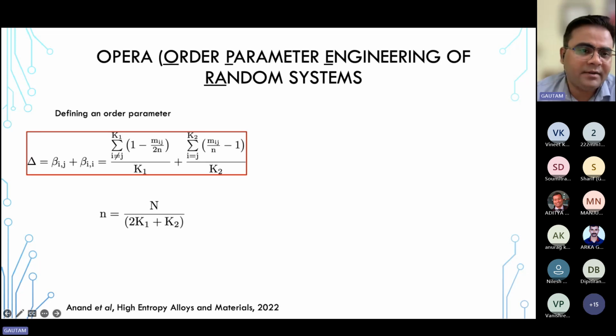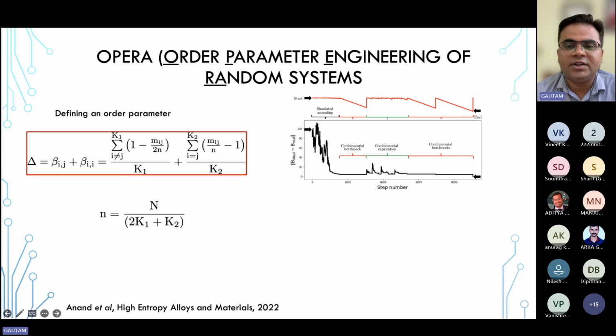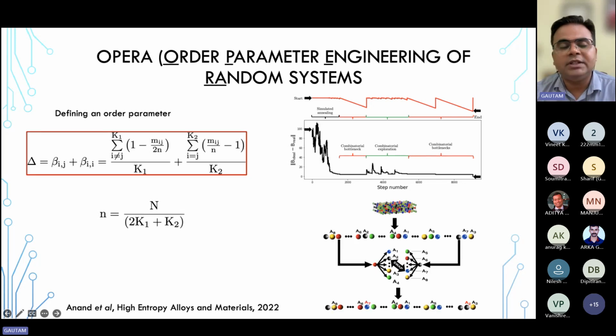First of all, we define an order parameter, the delta parameter, where beta is defined for unlike bonds and like bonds in the system. So you have a supercell. Depending upon the number of components, K1 represents the number of unlike bonds in the system. Small n represents the number of atoms in the supercell, divided by K1, which as I mentioned is the number of unlike bonds, and K2 is the number of like bonds in the system. With this, we define a delta parameter in the system. We first generated a random structure, where B ideal is the number of bonds the system needs to have, and B real is the number of bonds you get in the system when you are just swapping the atoms without any energy calculation. So you can generate the random structures, and then you can introduce the chemical short range order once you have got the random structure.